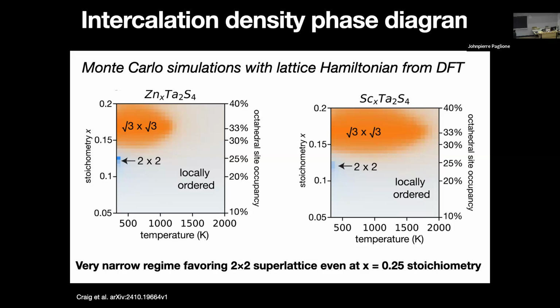And what we found, to cut to the chase, is that if you're targeting the 0.25 stoichiometry, there is a very, very small window or regime, in temperature versus stoichiometry. This stoichiometry, by the way, is for a bilayer, so it's basically half or so the value you expect for the bulk. But it turns out there's a very, very small window where you would expect the long-range 2x2 to be the low energy configuration.